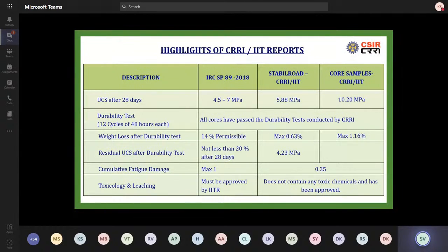Again, if you remember, we talked about residual UCS after the durability test. It should not be less than 20% after 28 days. In our case, actually, it's gone up. The cumulative fatigue damage test has also been done, and it was 0.35. Toxicology, like I said, has been done by IITR.